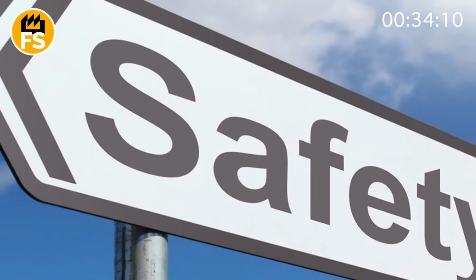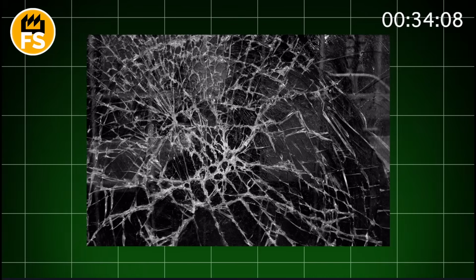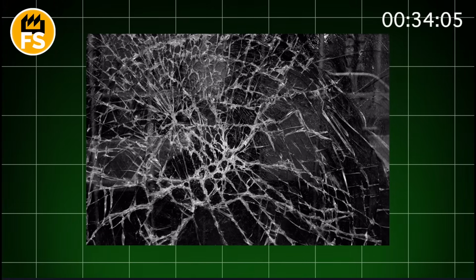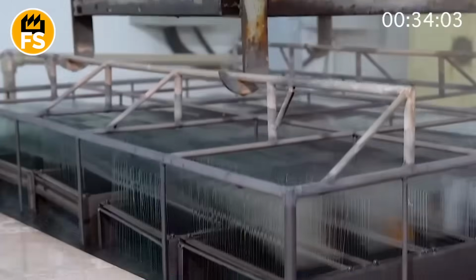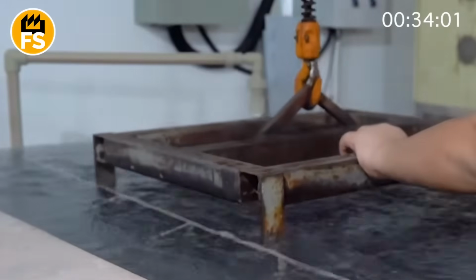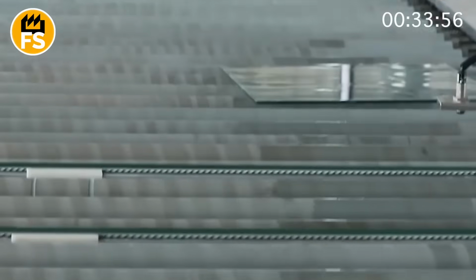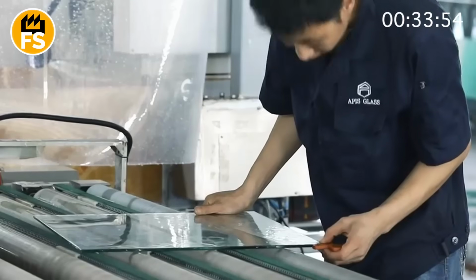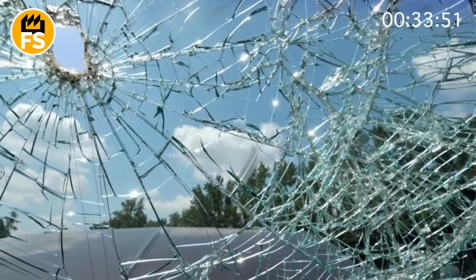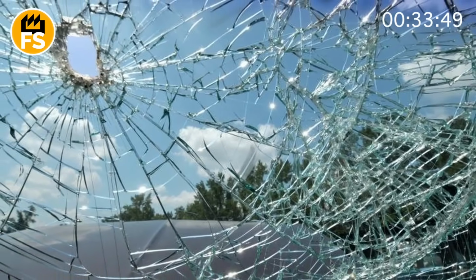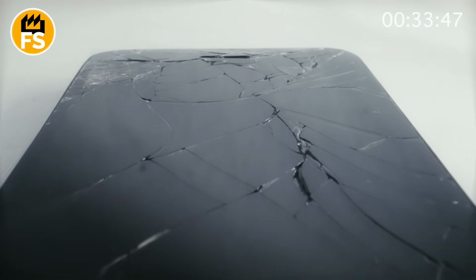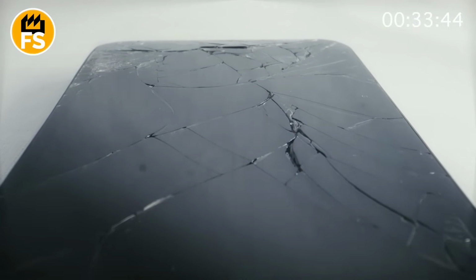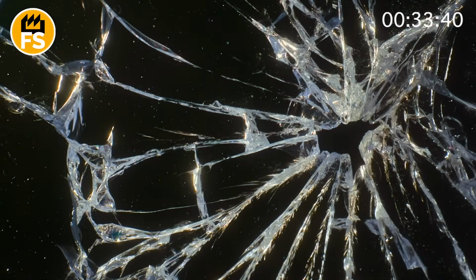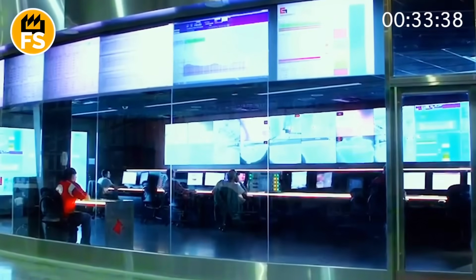When ordinary glass breaks, it forms long, sharp, dagger-like shards capable of causing serious injuries. When tempered glass finally reaches its breaking point, something completely different happens. All that colossal accumulated energy of compression and tension is released simultaneously across the entire sheet. This causes the glass not to crack, but to instantly shatter into thousands of small, pebble-like pieces with dull edges. This is the very same famous crumb you've seen on the side of the road after an accident.